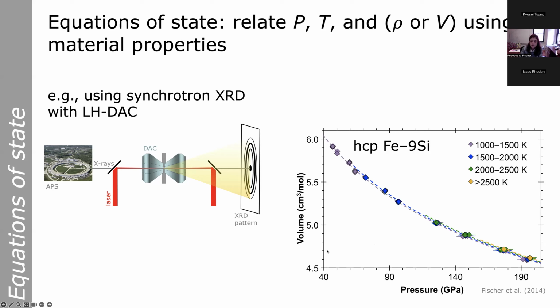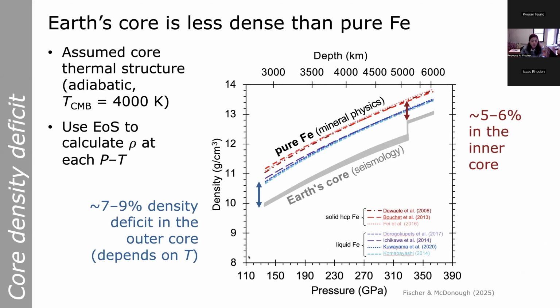Here I'm showing the molar volume of HCP alloy with 9 weight% silicon in it as a function of pressure. The symbols are data color-coded by temperature, and the dashed lines are the fitted equation of state. So with these equations of state, then we can calculate the density of these materials at any pressure and temperature that we're interested in. So we're going to start by doing this for pure iron.